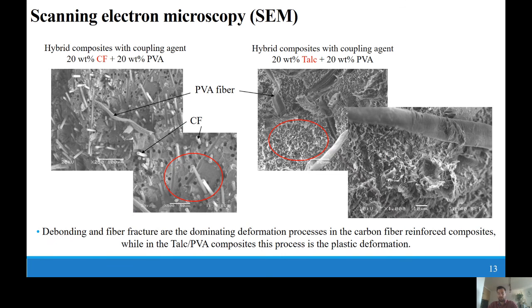So in order to identify the deformation processes occurring during the failure, images were taken of the fracture surface of the composite using a scanning electron microscope. In both carbon fiber PVA and talc PVA composites, the fracture and the pull out of the PVA fibers is visible. In the case of carbon fiber composites, the fracture and pull out of the fibers can be seen, while in the case of talc reinforced composites, the debonding of the talc and the plastic deformation of the matrix around the talc particles is visible. These local deformation processes consume more or less the same energy during the failure, as we saw from the previous slides.